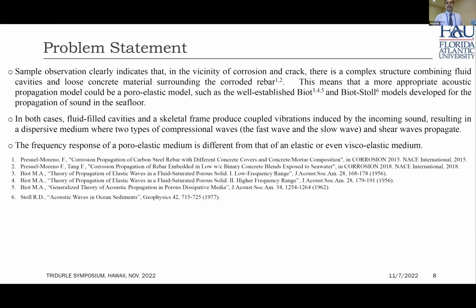Biot originally developed a model which is very commonly used in the field of sediment acoustics. It was expanded by Biot-Stoll, and then I did quite a bit of work over the years based on the work from Stoll to account for the gradual changes of the properties of the material as we go deeper and deeper, which is perfect to mimic the formation of early cracks around the corroding rebar. One thing that's important is that this is a frequency-based model. So we model at every single frequency in ultrasonics the response of the rebar and the concrete, the reinforced concrete.